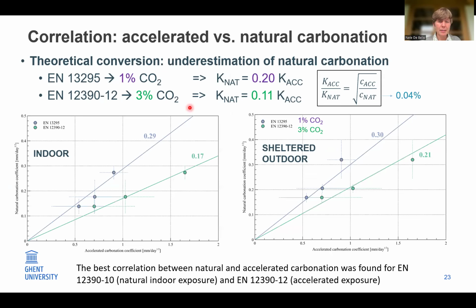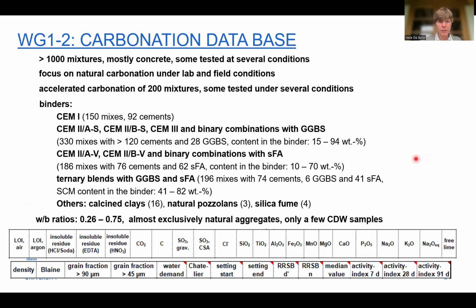We then also tried to correlate the accelerated with the natural carbonation conditions. And theoretically, if you look at the square root of concentration relationship with natural carbonation CO2 values of 0.04%, and then for accelerated carbonation, for instance, 1%, we would obtain a conversion factor of 0.2. And for 3% in accelerated conditions, it would be 0.11. However, in reality, for instance, here in sheltered outdoor conditions, you see that the actual coefficients were quite a bit higher. So this means actually that the theoretical relation would lead to an underestimation of the real natural carbonation rate if you start from accelerated tests.